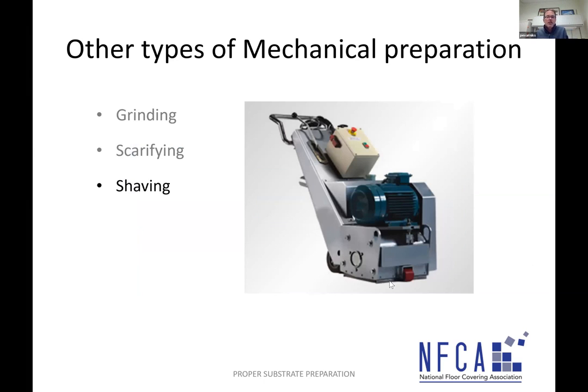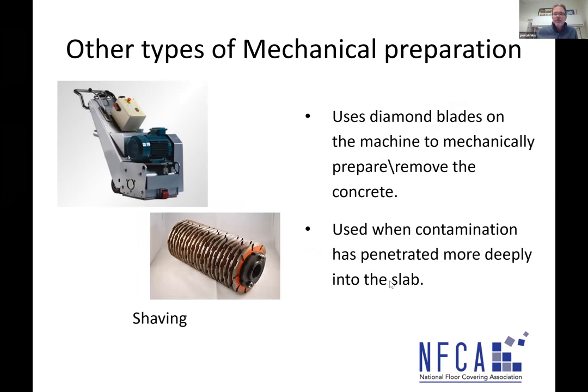One of the newer methods, I'm not sure that everybody's aware of or has seen, is called shaving. Basically, concrete shaving, if you will. When we take a look at shaving, it has a single axle with a number of diamond blades on this axle, and this axle spins at a very high velocity. You're able to dial down this axle towards the concrete and set it at a required depth, whether it's hitting the concrete at an eighth inch or going down into maybe a quarter inch of the concrete. And shaving's used when you have more deep contamination in the concrete.